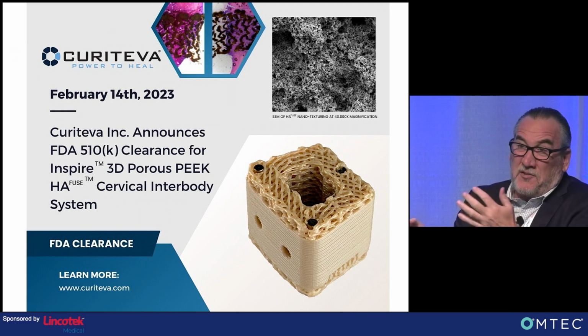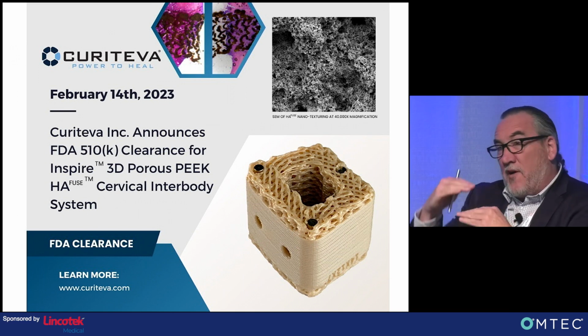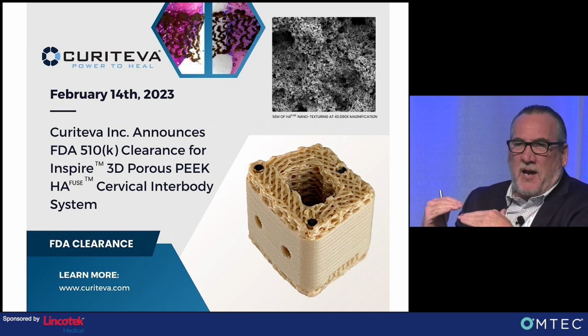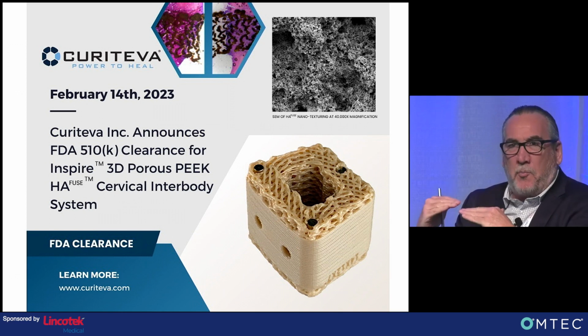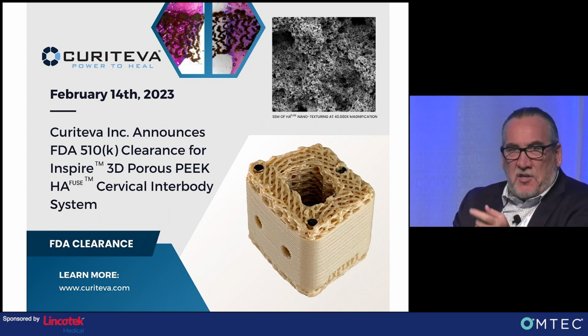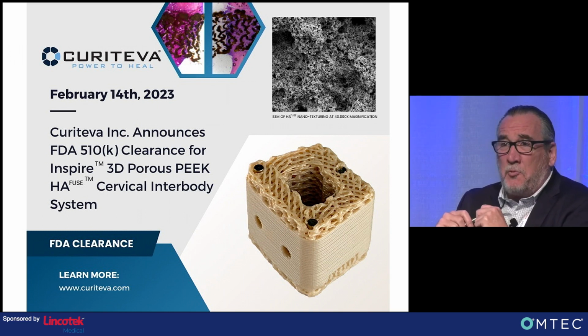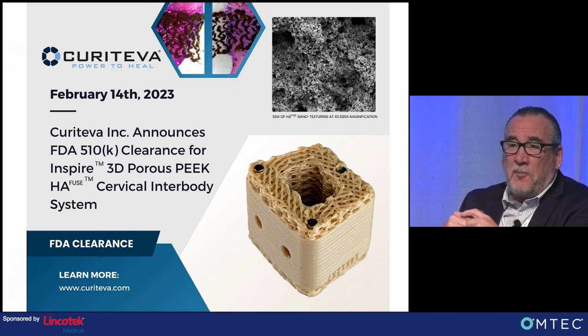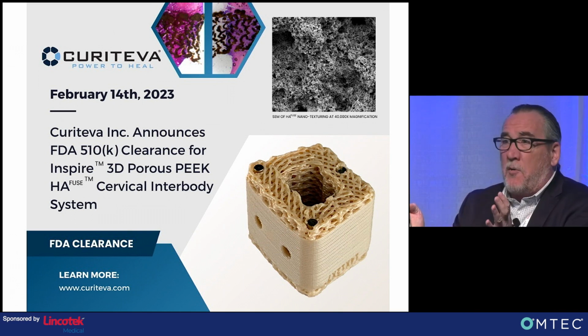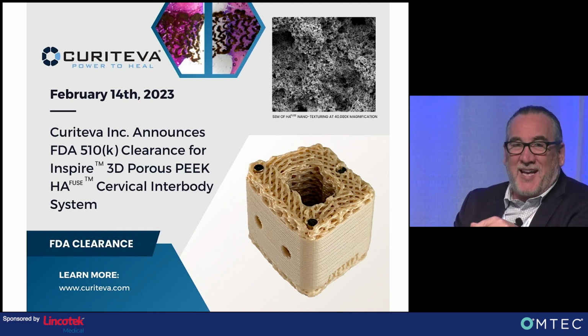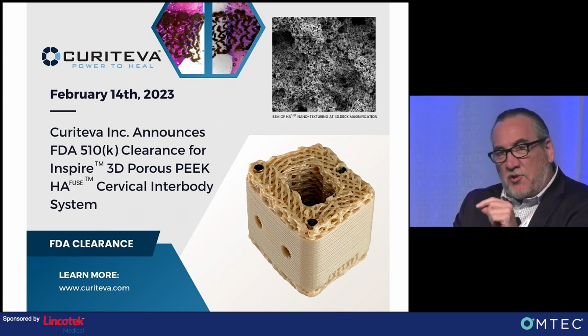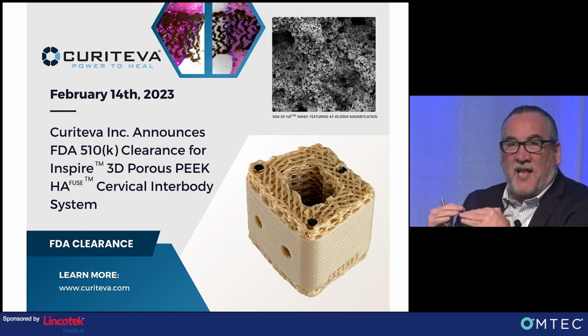Some of them are 2,000, 3,000 newtons, and they will fail catastrophically, meaning likely because of the large graft windows, they will buckle completely. This implant went up to 25,000 newtons, hit the limit of the load cell, and we stopped the test. It deformed a few millimeters, but it didn't fail catastrophically. That's even in a porous implant, that's the degree of toughness that you can get with strain-induced crystallinity of these strands that are holding that lattice together.